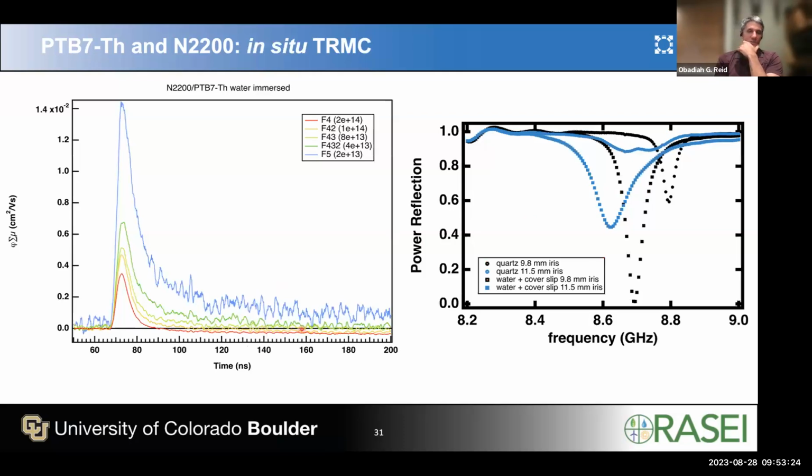So there's one surprising thing about this microwave conductivity data that you may squint at if you're a spectroscopist, which is that for the higher fluence transients, you start to cross through zero. And this, I think we understand, it's actually caused by a transient change in the dielectric constant of the water, because when you hit it with the laser pulse, its temperature changes ever so slightly, and that change in temperature changes its dielectric constant.